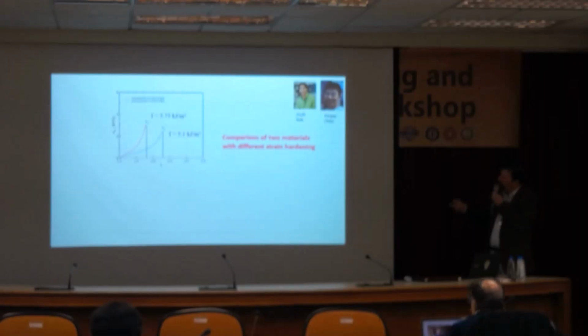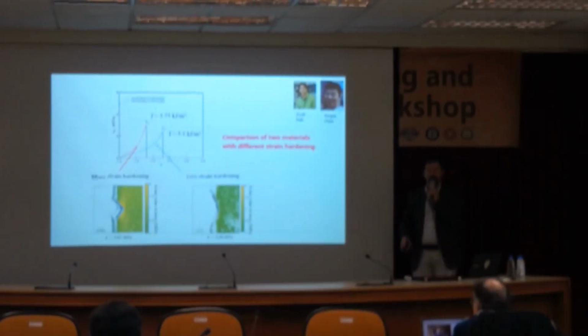And here I'm going to show you two images at two different points. One is the more strain hardening. This is color coded, this is 4 and this is 2 MPa. And you can see directly the stress distribution. This is not that easy to do. There's a number of techniques that give you the strain, for example digital image correlation, particle tracking, but to get directly the stress, you have to have a stress probe inside the material.